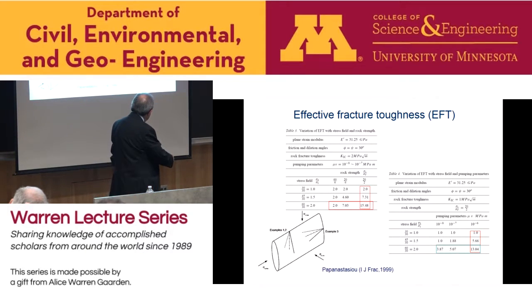And in this case here, we show the sensitivity of the increase in the apparent toughness to the pumping parameters. Again, pumping parameters, when we move horizontally here, we have high viscosity or high pumping rates in this column here. And in each row, we go to highly anisotropic stress field. Highly anisotropic stress field and high values of pumping parameters give again a high value of the effective fracture toughness.